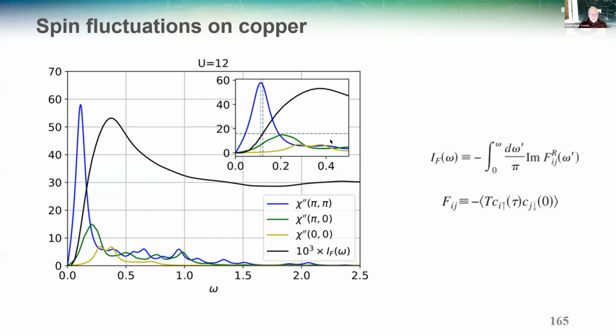Okay, this is a blow up of this whole diagram here. What's the blue curve here is the spin fluctuations at pi pi, and you see that they have some typical energy, and you can show that it scales like J. It's not equal to J, but it scales like J. And in black here is this integral as a function of the cutoff. If you go from 0 to infinity, that's the superconducting order parameter, the equal time. So this black curve here is equal to the order parameter in the ground state. And what you see is that the order parameter picks up strength at the same time as the spin fluctuations. There's an overshoot, and it eventually comes down.